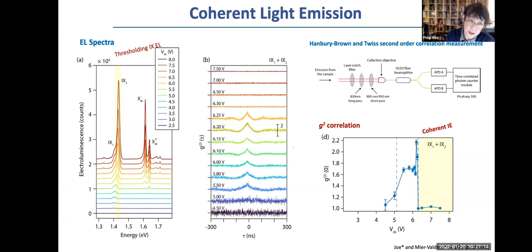What you see in this example is that although there is really encouraging progress happening, we keep struggling with how to control this lifetime versus the coherence in the system. And part of the reason for this struggle to create exciton condensation is that an exciton, as the name indicates, is not a ground state. It is always created by excitation, either light or electron-hole injection. And therefore, creating this thermodynamic ground state, where condensation should happen, is in some sense analogical.